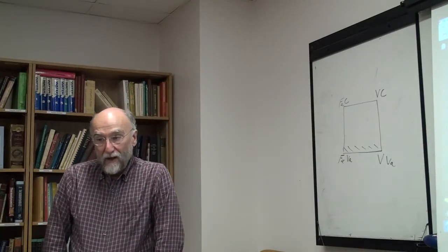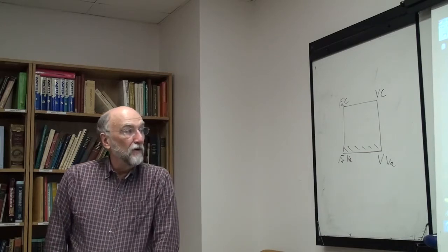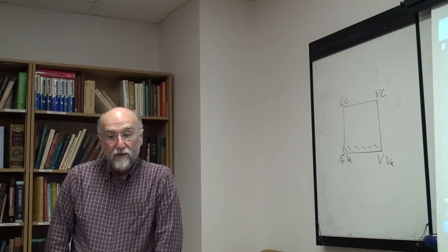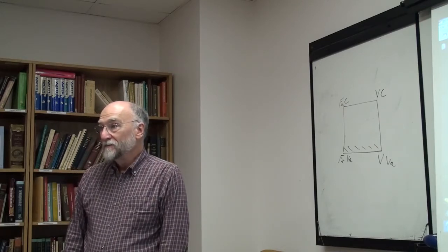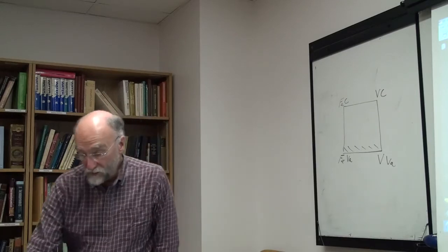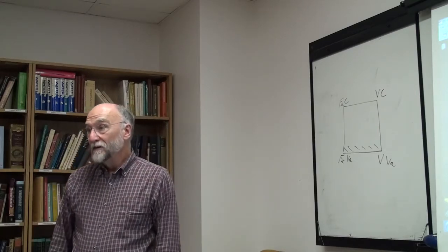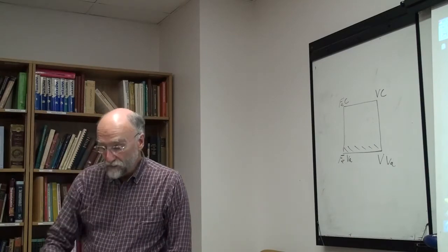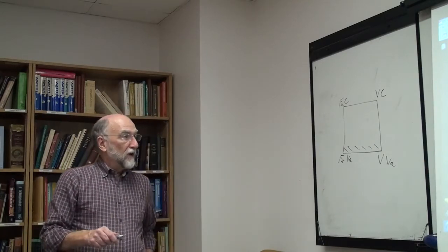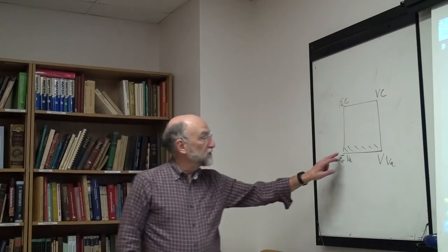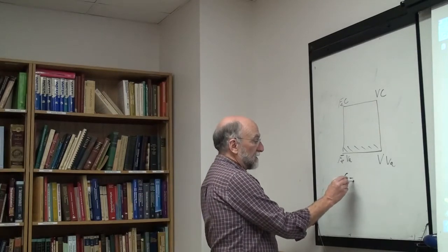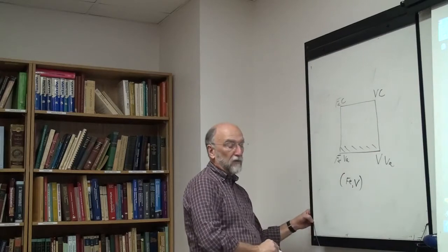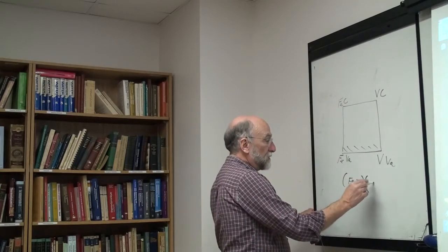So we have 2 sublattices here. On one sublattice, the iron and vanadium are randomly mixed, and on the other sublattice, the carbon and the empty sites are randomly mixed. Most of the sites on the interstitial lattice are empty, and the carbon is going randomly into those sites. So we're going to use the sublattice model, and we're going to write it this way. Here I'm going to write in this corner. Remember, each corner, the model is as follows. Iron and vanadium are on that sublattice, and on the other sublattice you have carbon and vacant lattice sites.